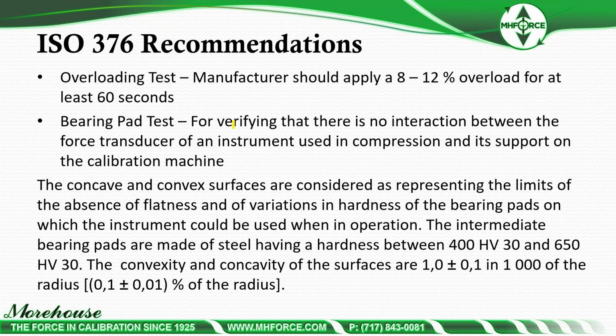Overload test, manufacturer should apply 8 to 12% overload for at least 60 seconds. Bearing pad test. This one's an interesting test. If you're using critical applications or you want to know how good your load cell is, this test is for verifying that there is no interaction between the force transducer of an instrument used in compression and its support on the calibration machine. The concave and convex surfaces are considered as representing the limits of absence of flatness and variations in hardness of the bearing pads on which the instrument could be used when in operation.